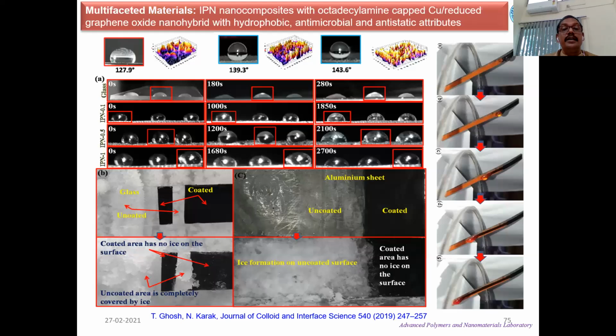This interpenetrating polymer network of polyurethane and polystyrene with octadecyl amine capped copper and reduced graphene oxide based nanocomposite shows hydrophobic surface, antimicrobial surface, and anti-static surface. We have shown up to 143 degrees, near super hydrophobicity.